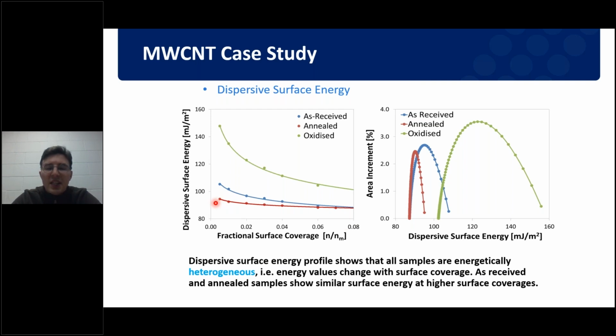Now we can see that the annealing process has somewhat relaxed. It has lowered the dispersive surface energy of my carbon nanotubes. And it has also made it more homogeneous. So not only has it lowered the surface energy altogether, but it's made the difference between the highest energy site and the lowest energy site much smaller. It's a much more narrow surface energy distribution. And we can see the opposite effect is happening with our sample that has been oxidized.